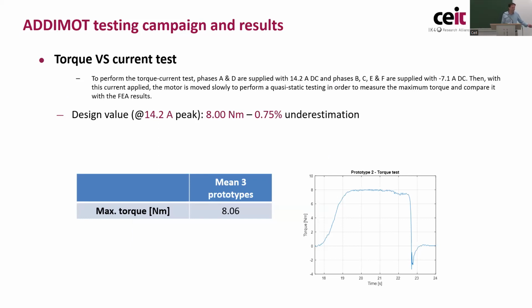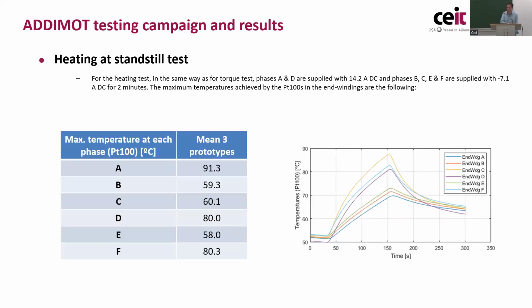Okay. Thank you. A very simple torque versus current test. Unfortunately, we haven't had the converter to drive properly the motor, so we proceed with a DC current test and quasi-statically move the rotor so that we measure the torque versus angle of the motor. We measure the mean value for the 3 prototypes of 8.06 Newton meter for the given current, which is a very good result compared with the estimation. There is almost no discrepancy. So here the objective of the standstill torque was achieved.